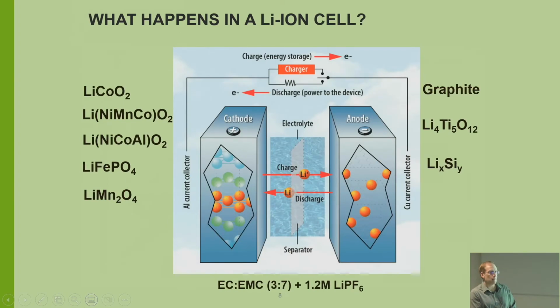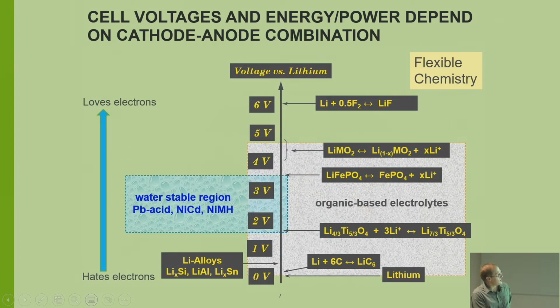So you're saying that's the cell voltage? Yes. Well, it depends. You have to have something that gives up an electron and something that takes an electron, so you need 2 half cells to make a full cell. You take this one reaction where it gives up a lithium and also an electron with it, and that's basically a charging situation. You push that lithium into the graphite down here at about 100 millivolts. So the difference between that line and that line is basically your theoretical voltage.